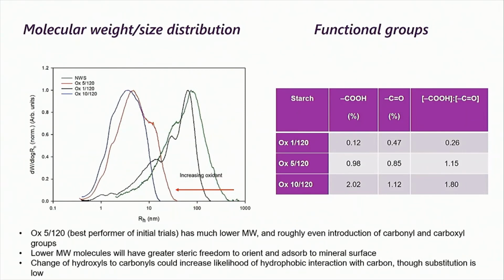If you look at the association of the functional groups, the carbonyls and carboxyls that are produced on the way to this, you can see there that at 1% you've got slightly more carbonyls than carboxyls, and then as you go to the higher percentage of oxidant, that will invert and you'll get more carboxyls than carbonyls. We just so happen to see in this case with the 5% that our carbonyl to carboxyl ratio of around 1 seems to be achieving something we want.